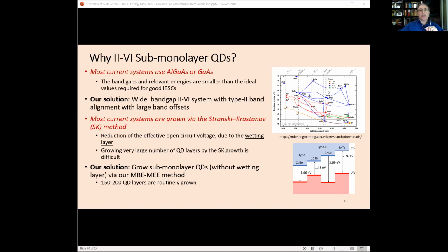And it turns out that our material system will work, which is shown here. And the specific parameters shown in this graph are actually close to 2 electron volts. The second important point is that the previous systems, the III-V systems people work on, are grown by the so-called Stranski-Krastanov method. Again, without going into detail, it has